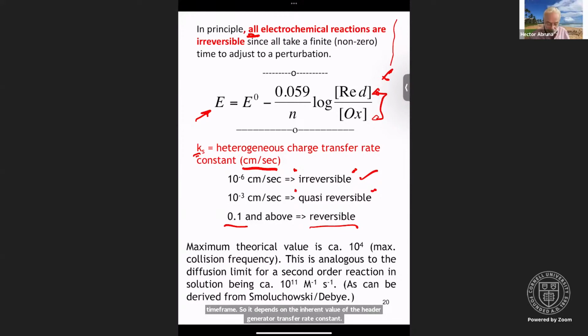So it depends on the inherent value of the heterogeneous charge transfer rate constant and the technique you use to measure that value. There is a maximum theoretical value for Ks of approximately 10 to the fourth, and this relates to the surface collision frequency. Remember, you have a molecule that has to interact with the surface, and the rate of electron transfer cannot be any faster than that collision frequency, because that's required for the process to take place.